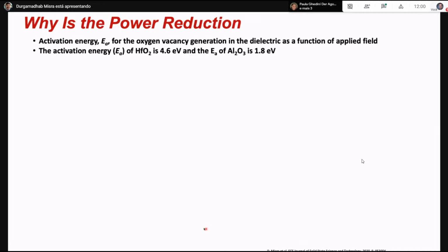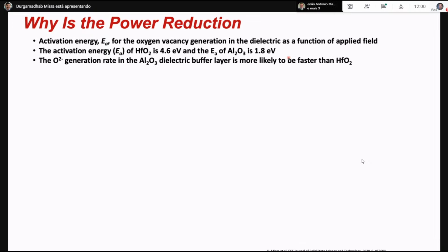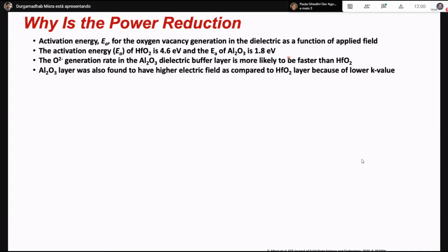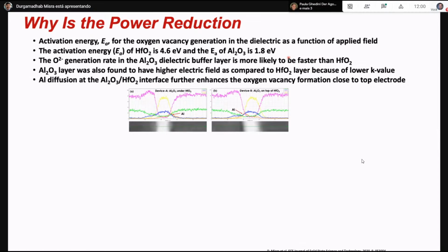And then if you look at the hafnium oxide, it is 4.6 electron volt. And aluminum oxide is 1.8 electron volt. That means the aluminum oxide is much faster compared to hafnium oxide in oxygen vacancy generation. The aluminum oxide layer also sees a high dielectric field because it has a low dielectric constant. If you apply a voltage, there is a large field drop across the low dielectric material compared to the high dielectric material. So that also enhances the oxygen vacancy formation.